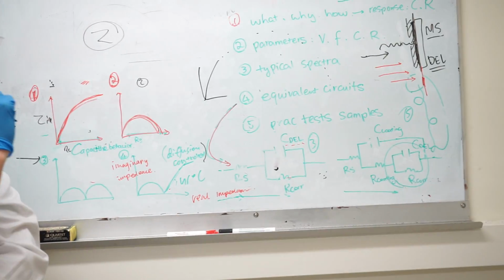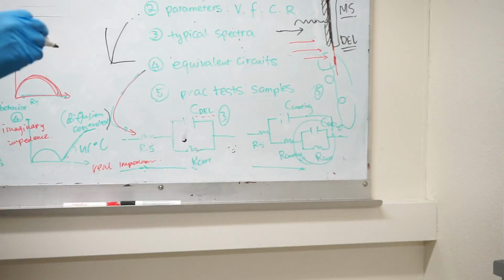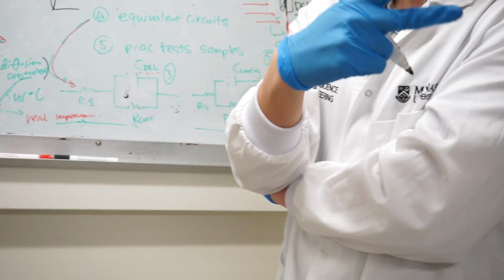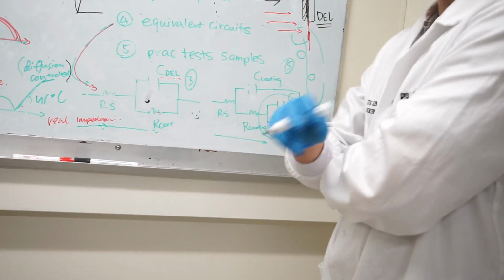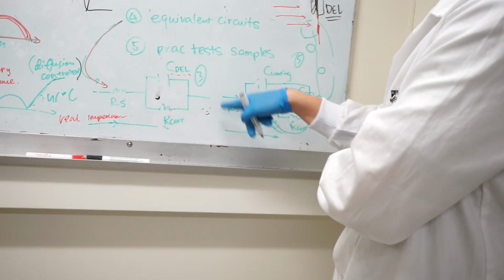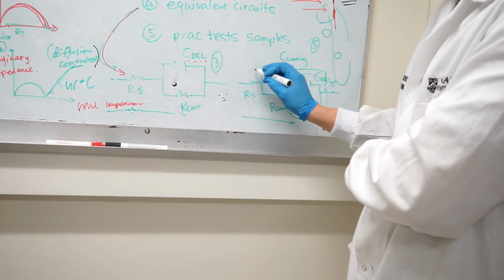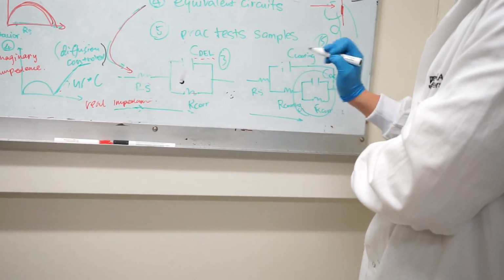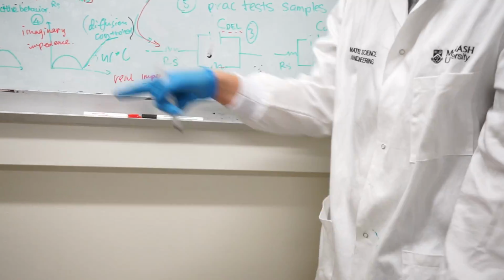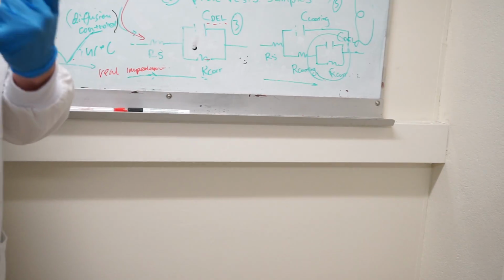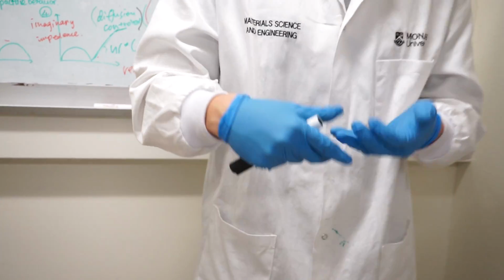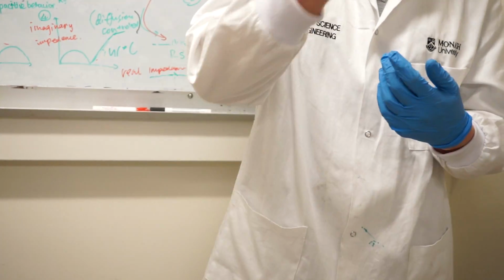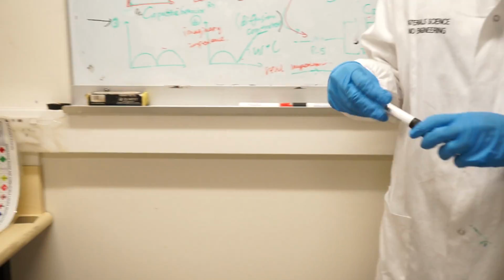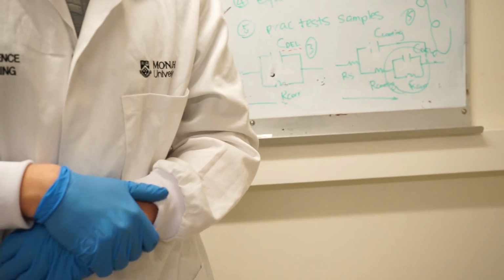Alright? So now in the case of the scribed one, if you have a damage on your coating, you now have two signals coming. One is from the coating and the other one is from the double layer. So therefore you have this typical circuit where you have the solution resistance, the coating resistance and capacitance, and the double layer capacitance and resistance. That's why you have two semicircles, because you have two more elements in the system. So today we're gonna do the impedance test for one uncoated mild steel, a coated mild steel, and a coated mild steel with a scribe on the surface. We have these three scenarios, and we're just gonna run the test to see how the curves are.